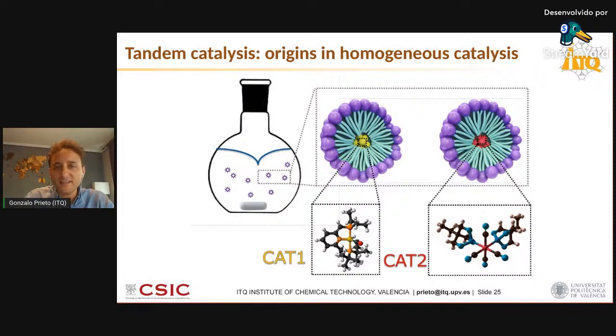So compartmentalizing them was beneficial, and that's something that in the initial papers dealing with tandem catalysis was achieved by engaging each of the catalysts in different compartments, which were still permeable to reactants and products, so that the two could exchange reactants and products without enabling direct contact between the two catalysts. This was, for instance, using dendrimer vesicles, using micelles, and so on to keep the two catalysts away from each other.